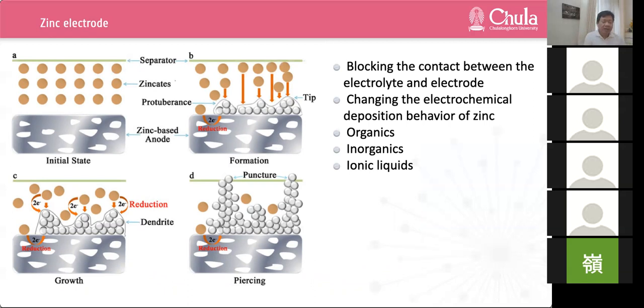Dendrite formation on the anode surface generally occurs in alkaline zinc air batteries during charging. The formation mechanism of zinc dendrite has been studied. The charging reaction of the zinc electrode is mainly influenced by the liquid phase mass transfer, in which large concentration polarization forms in the low concentration of active component near the electrode surface.